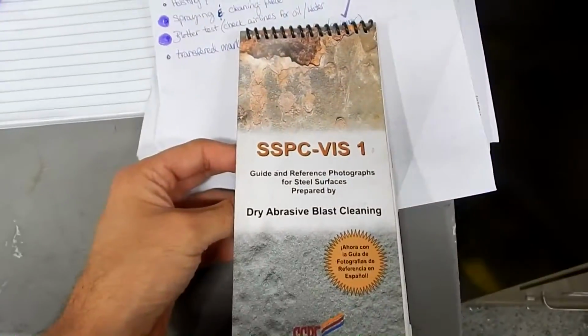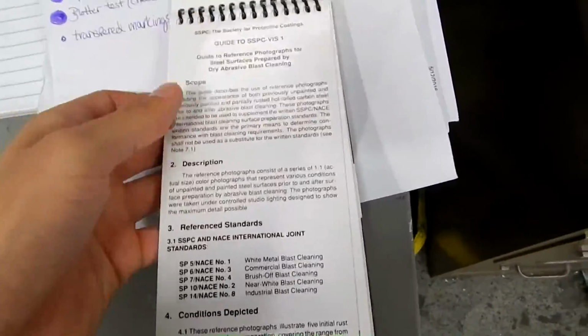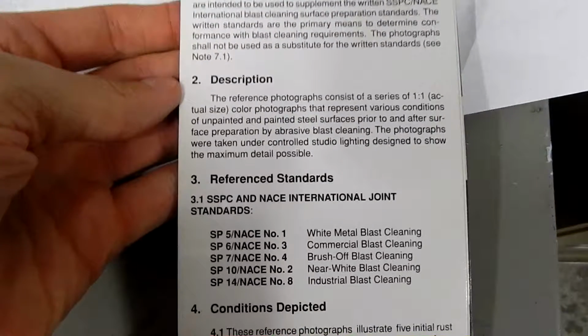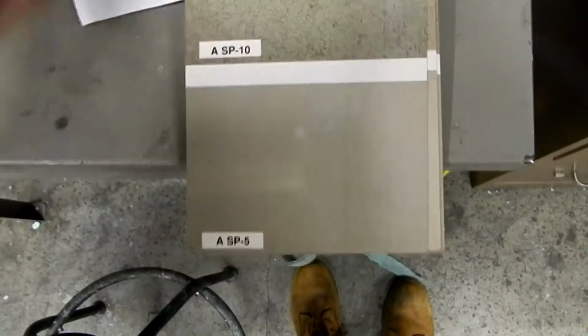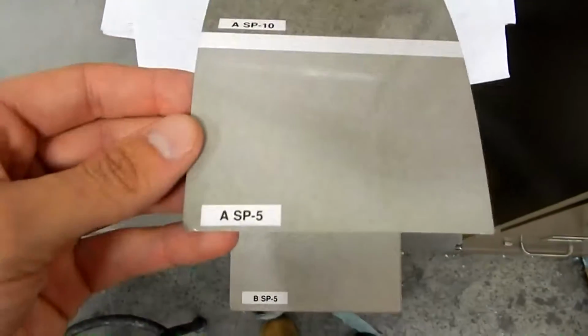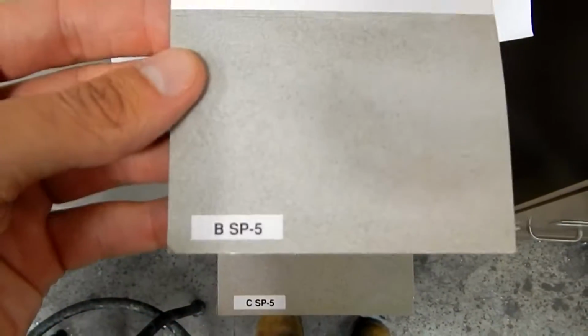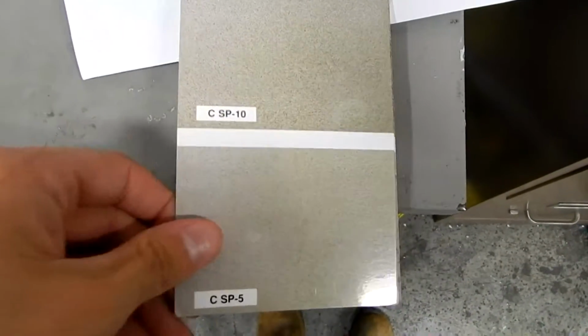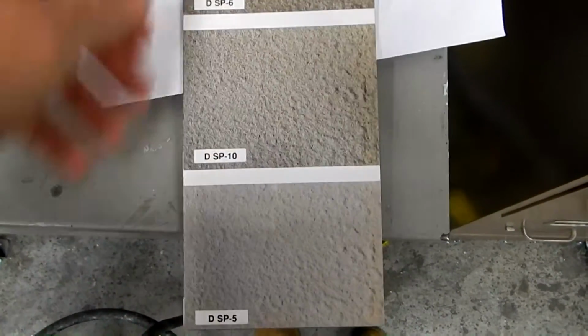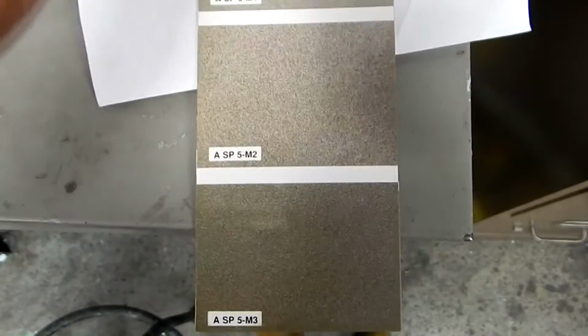Step 4. Verify surface preparation. In order to achieve best results, the surface of the piece to be coated after blasting must be at least NACE number 2. NACE number 2 is a near white metal blast clean surface. When viewed without magnification, the surface shall be free of all visible oil, grease, dust, dirt, mill scale, rust, coating, oxides, corrosion products, and any other foreign matter except for staining.